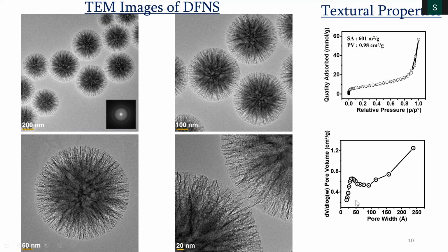So when I say pore size, ideally these are the distance between the two fibers, right, this way. So when I move from center to the periphery of the sphere, you can see now the distances are increasing. And that's what you see here. You have around 45 angstrom, and then that's around 5 nanometer, and then you have pores up to 25 nanometer. So this allows you to even have bigger molecule to diffuse in. And if you want to do a catalysis with a bigger molecule, that can also be used.